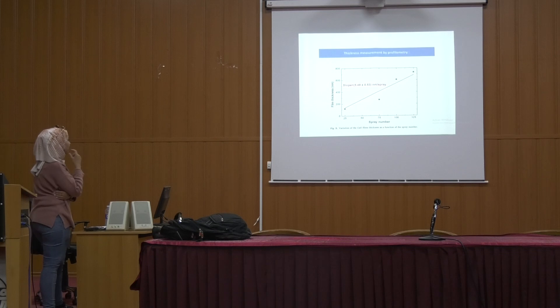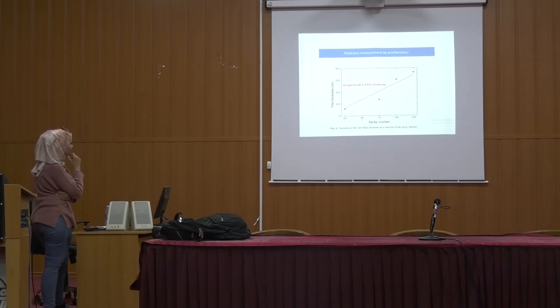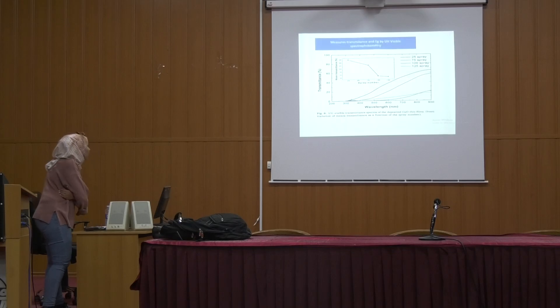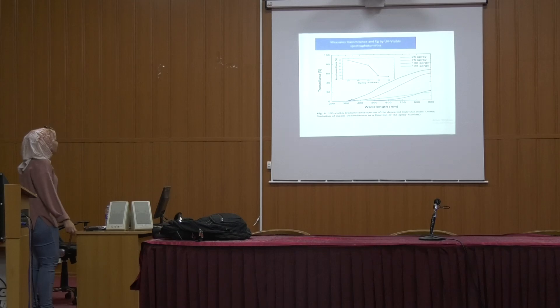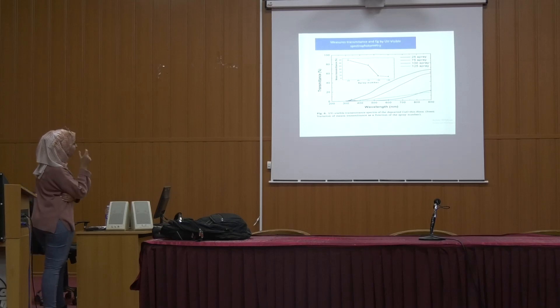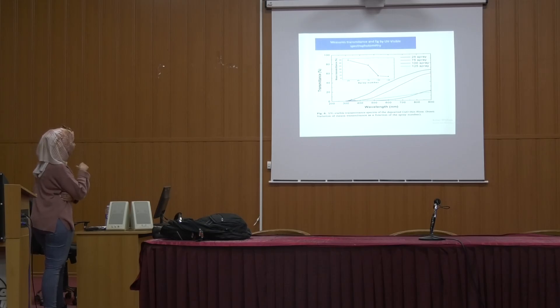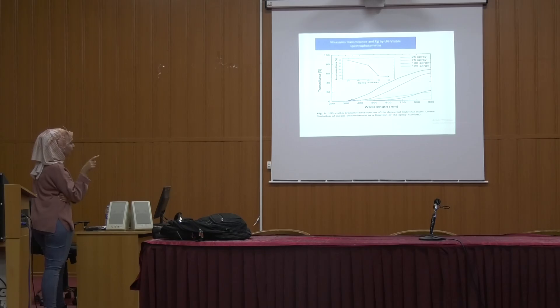This figure shows that the dislocation density of the copper oxide films decreases as the spray number increases, and depends strongly on the nature of the crystal. The UV-visible transmission spectra of the deposited films show that the transmittance in the range of 400–800 nanometers decreases as a function of spray number. This may be due to the higher electronic transitions between the valence and conduction bands, which is called absorption.